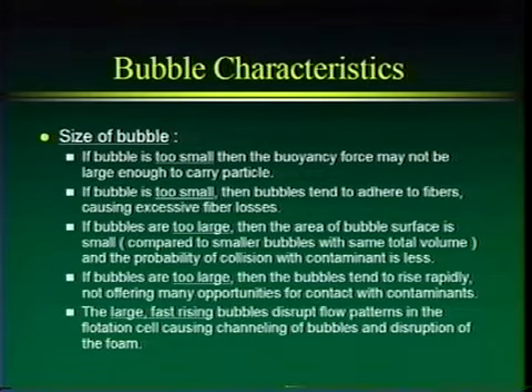Finally, the large, fast rising bubbles may disrupt the flow patterns in the flotation cell, causing channeling of bubbles. So if you have a very large bubble, what can happen is that very large bubble goes up, and then it causes a path, it separates all the fibers in that little channel, and then more air bubbles will channel up through that one channel in our flotation cell. And if you have just air bubbles floating up in this one line going straight up, then all these other areas in our flotation cell aren't seeing air bubbles. So this channeling of large bubbles can be an issue.